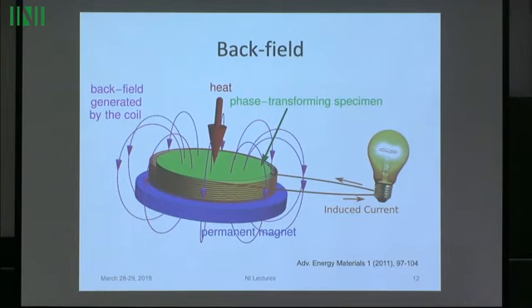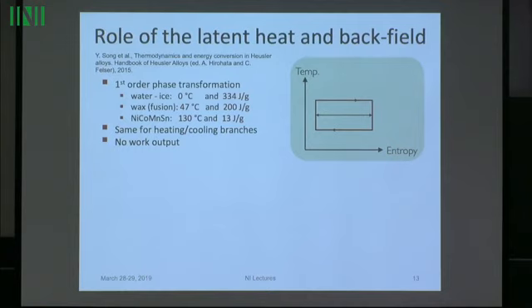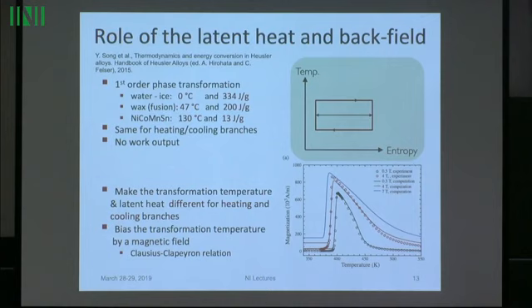So in other words, on this slide, if you just went back and forth through a phase transformation, keeping the temperature the same, there would be no area in this graph. In the context of the first lecture, you would generate no electricity. So you need to bias it so that the transformation temperature on heating is different from the transformation temperature on cooling. The backfield does exactly that, together with energy minimization, of course. The energy minimization tells you that the transformation temperature will be different under different applied fields. So that's the basic effect.